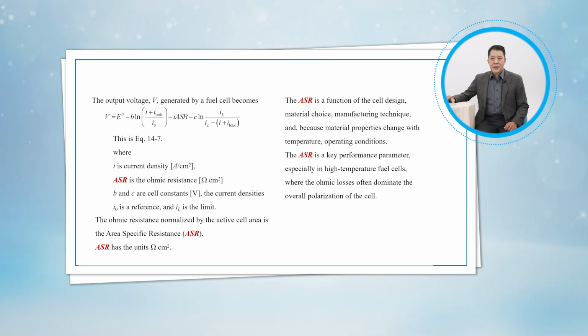Together with the resistivities of the materials used, they yield the bulk ASR. The contact resistance cannot be calculated from fundamental data and is usually determined by difference between the measured total resistance and the computed bulk resistance. When using literature data for ASR, it is critical to verify the definition of ASR. Some researchers have defined ASRs to include the activation and concentration polarization as well as the ohmic polarization.